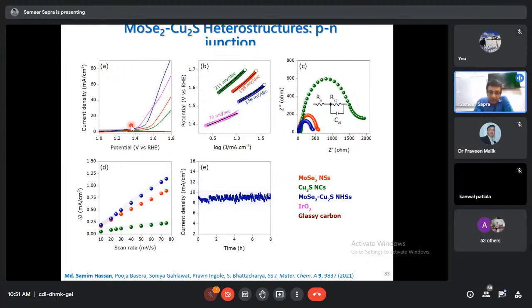Okay. And again, all these data that I'm showing you over here is essentially telling you all the various reasons I've discussed earlier, so I'll not go into that, except for panel D, where you can see that the electrochemical surface area is much higher when you have this molybdenum selenide cuprous sulfide as compared to just molybdenum selenide or cuprous sulfide. The electrochemical surface area is not just the area, but the active area, where the catalytic reactions can take place.